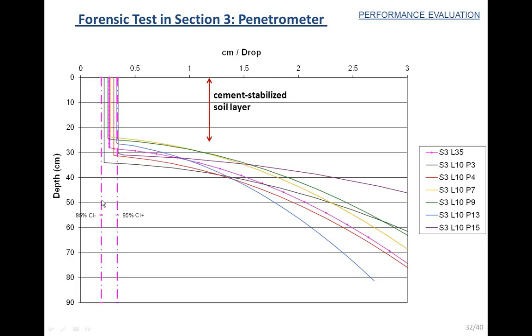The interesting thing is that here in pink color you can see the confidence interval for the penetration along a line that was far from the center of the wheel path. So this interval of penetration is representative of the penetration in an area where there is no damage. This pink is the interval for the material with no damage, and then each one of these lines corresponds to different points along the center of the wheel path. So we were expecting this material to be highly damaged, so we were expecting this penetration level to be here.